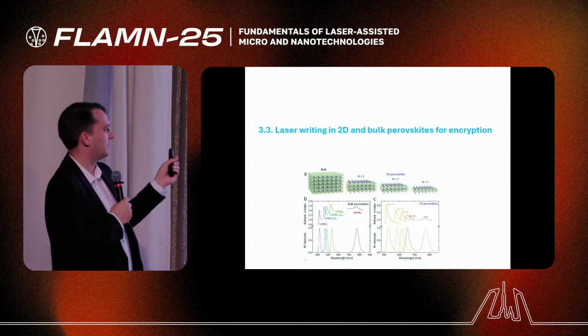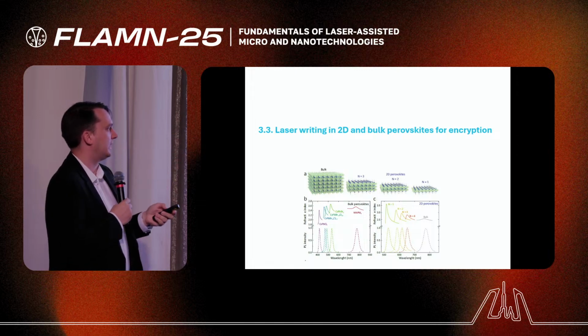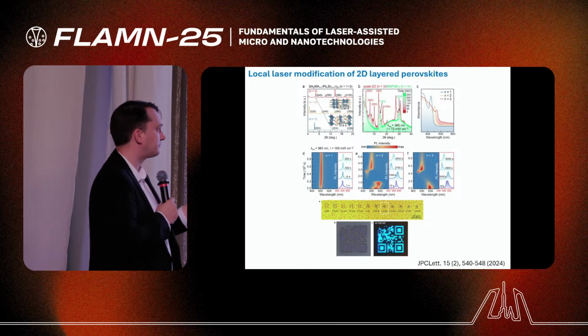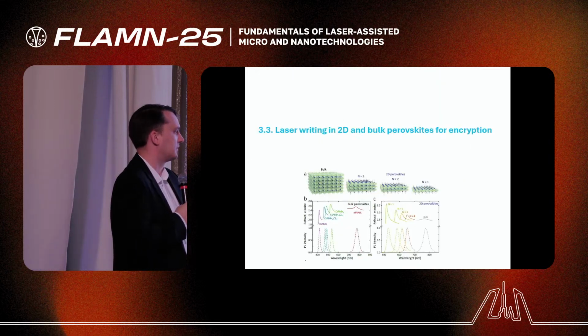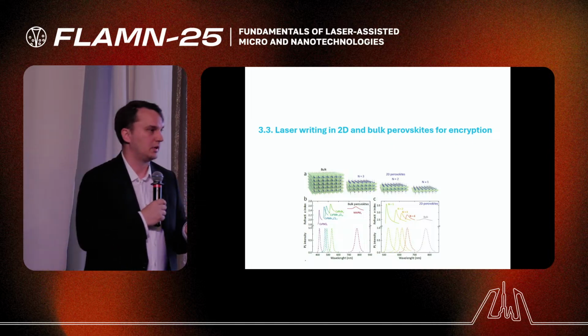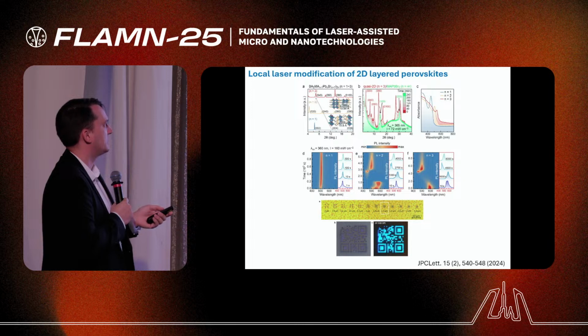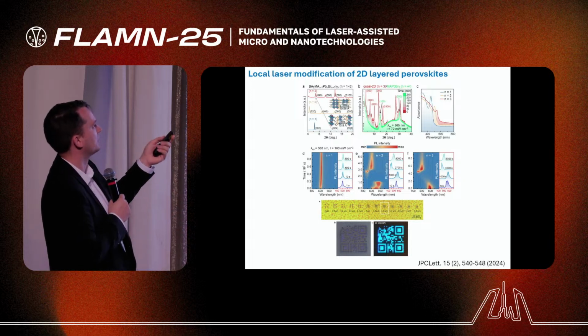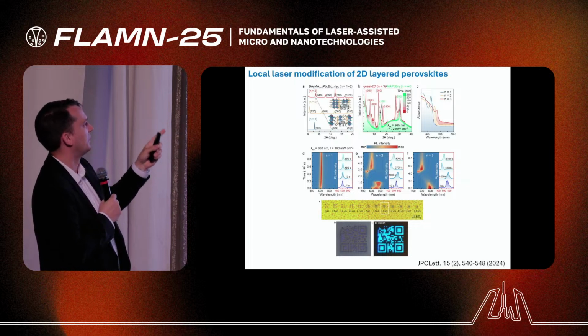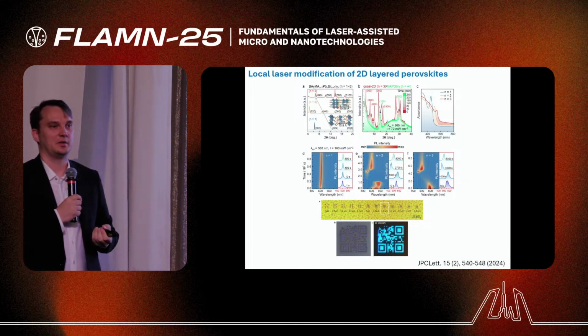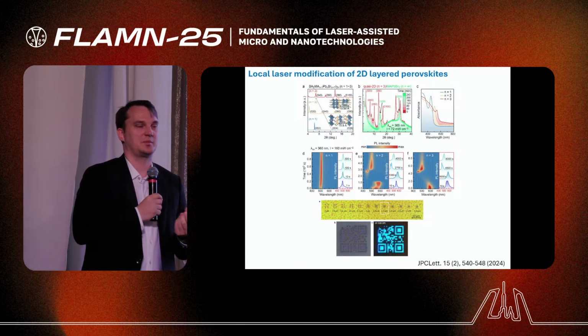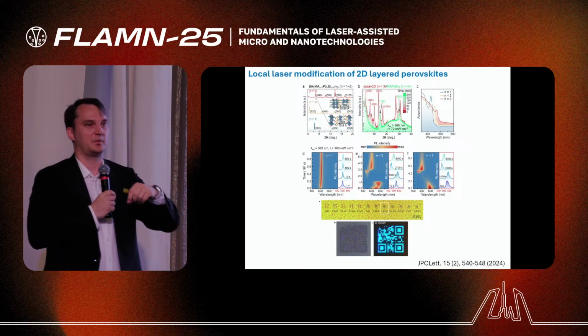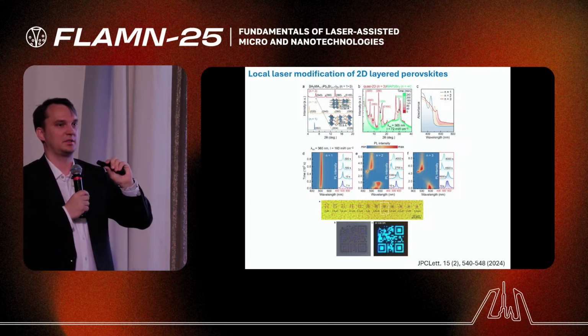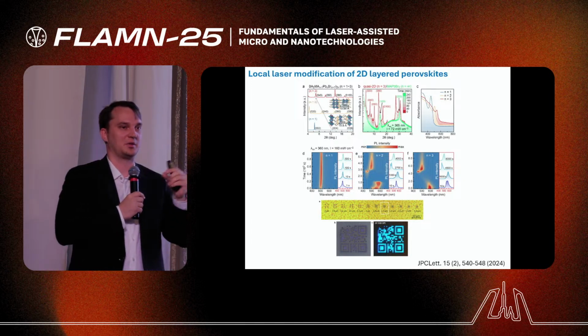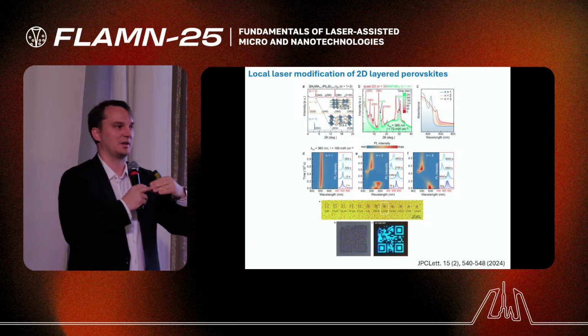As you can see here, we have different emission wavelengths for different numbers of layers, and different compositions also have different wavelengths. So we can combine these two properties to create some patterns on perovskite. We have a quite complicated two-dimensional material like butylamine, methylammonium, lead, bromide, iodine perovskite. The idea was to create such a metastable material. Then if we illuminate it with relatively high intensity light, we can convert it from the two-dimensional case to the three-dimensional case, because we can evaporate some ligands and just make the material bulk.